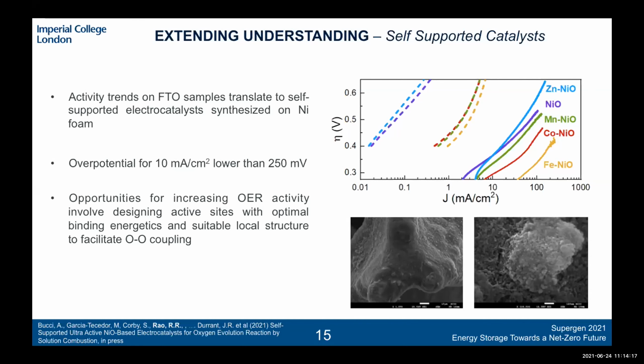And quite interestingly, to achieve 10 milliamps per centimeter square, which is the current density at which people benchmark these catalysts, we need an overpotential of 250 millivolts, which is quite close to state of the art for water oxidation materials.